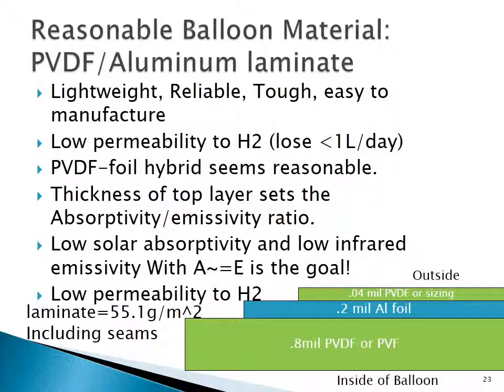So I think PVDF is a good choice of materials for the film on that balloon, and the reason is it has some excellent properties for the environments that it's going to face. It's very UV and ozone stable. It's tough. It's reliable, and 3M makes the Dyneon PVDF films with some plasticizer they add in for extended low temperature performance. Basically, it gives them plasticity below the glass transition temperature, and so they're reporting a brittleness temperature of less than minus 55 degrees Celsius, which makes it an excellent candidate for the temperature ranges that this system would operate in. And then lastly, the PVDF has a very low permeability to hydrogen and helium gas.